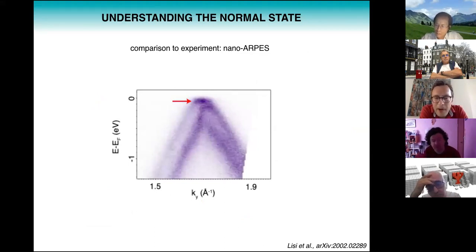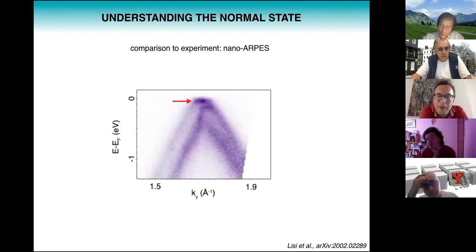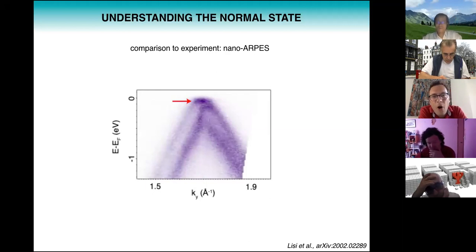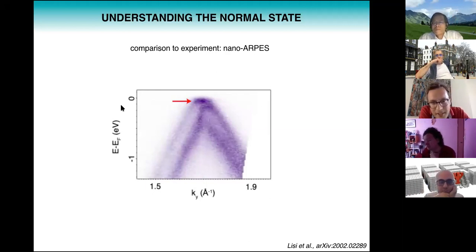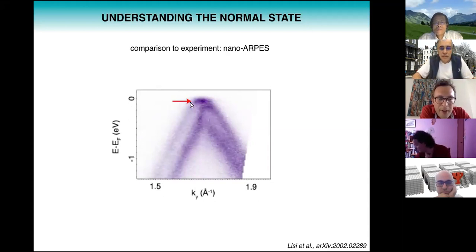So on Monday, I was asked about how one could ascertain that these flat bands are real, which of course is a good question since we're basically obsessing about them. And of course, the most direct probe of the band structure is ARPES. And quite recently, there was a group that did a nano-ARPES experiment on twisted bilayer graphene at the magic angle. And this is their result. What you see here on the y-axis is a very big energy scale from 0 to 1. This red arrow denotes the flat bands. The only thing you can really say is, yes, there are probably flat bands, which is a comforting knowledge that they do exist. But from ARPES, we can't really learn much about the flat band dispersion.